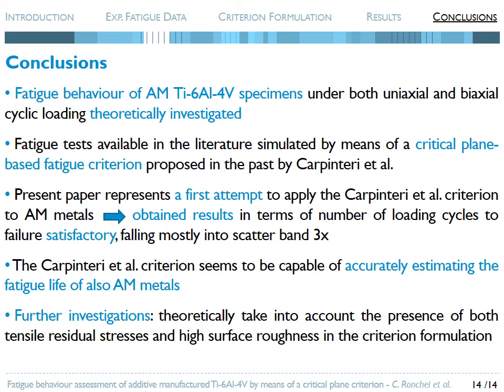Even if the present paper represents a first attempt to apply such a criterion to AM metals, the obtained results in terms of number of loading cycles to failure are satisfactory, falling mostly into scatter band 3x. Based on the above results, the Carpinteri et al. Criterion seems to be capable of accurately estimating the fatigue life of also AM metals. However, it can be said that further investigations are needed in order to theoretically take into account the presence of both tensile residual stresses and high surface roughness in the criterion formulation.